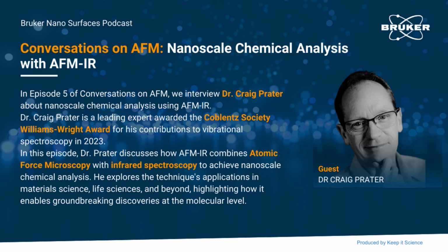And so a common use case in labs where they're using both AFM-IR and OPTIRs, they'll use OPTIR to measure large areas of the sample to understand the sort of micro scale chemical composition, structure, et cetera, and then identify regions of high interest where they want to get higher spatial resolution, and then that's where the AFM-IR comes in. So that's a great application example. As you mentioned, OPTIR, you scan larger sample areas and then you identify the regions of interest and use AFM-IR to really get in more depth into this with higher resolution to get more information.